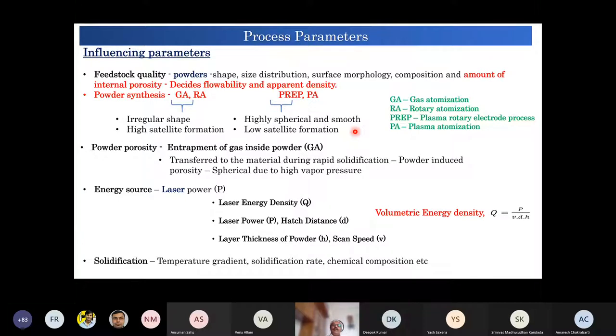Then in all these processes we have inevitably gases trapped inside the particle itself. Like when the sphere forms, there are inevitably gases trapped inside, because during rapid solidification it is never done in vacuum, it is always done in a gaseous atmosphere, and then there are some entrapped gases when the solidification takes place. So those things have to be taken into account.